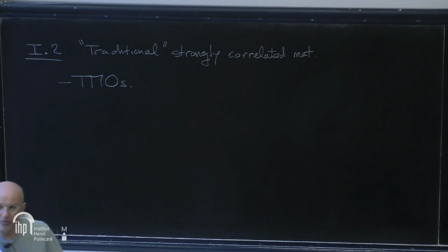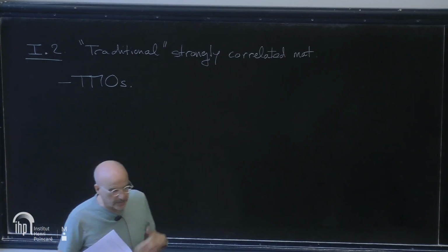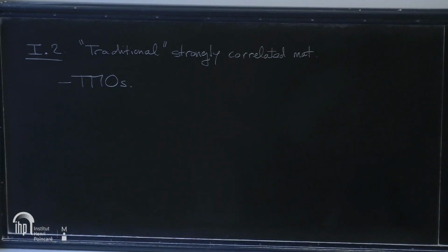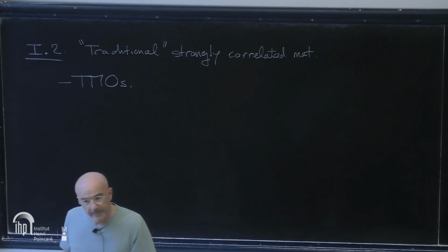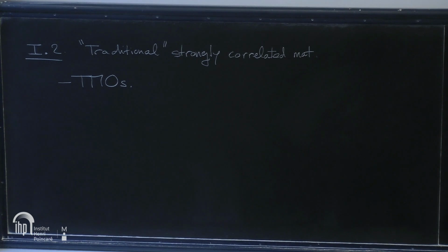You see that in the cold atom context, you know quite precisely what U is. You can also measure it in various spectroscopy experiments. While in the context of solid-state physics, it would be extremely naive to estimate U from just taking matrix elements of the bare Coulomb interaction. That would give values of order 20, 30 electron volts, much, much too large to be realistic. And the key phenomenon that reduces this value of U is screening, the fact that in a metal, if you put a test charge at long distance, the Coulomb potential is screened out and decays faster than 1/r, typically exponentially. And as a result, the strength of the effective Coulomb interaction seen by a given d band in an oxide, let's say, is more on the scale of a few electron volts. So it's reduced by basically an order of magnitude.